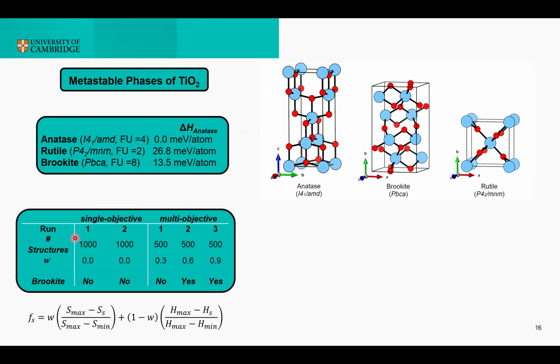Here you can see two classic searches, so single objectives based only on the enthalpy, where over 2 searches done on 1,000 structures each, Brookite was not found, while more symmetric structures like anatase and rutile were always identified, even if rutile in this case is calculated to be less stable. On the other hand, the new powder X-ray diffraction method seems to really outperform, since it can identify Brookite in less than half of the structures, actually just in a few hundred structures.